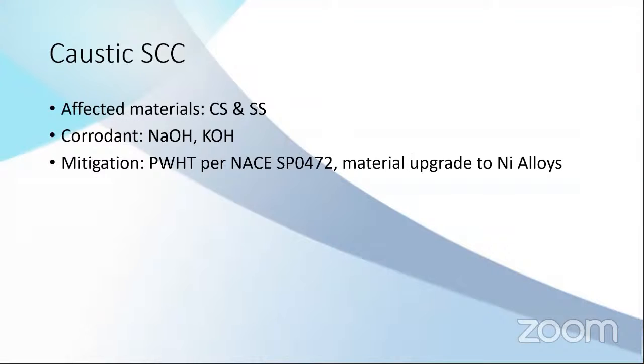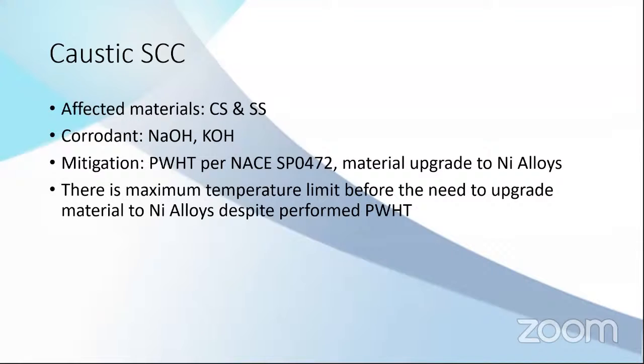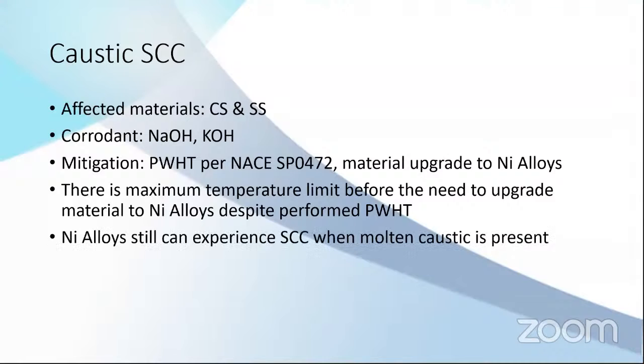There are two types of mitigation: post-weld heat treatment. But sometimes post-weld heat treatment is not enough, depend on the caustic concentration and temperature. The alternative is upgrade to nickel alloys, where it's more resistant. Yes, there is a maximum temperature limit before the need to upgrade material to nickel alloys, despite PWHT. PWHT just to extend the operational range, but not to all range of concentration and temperature.